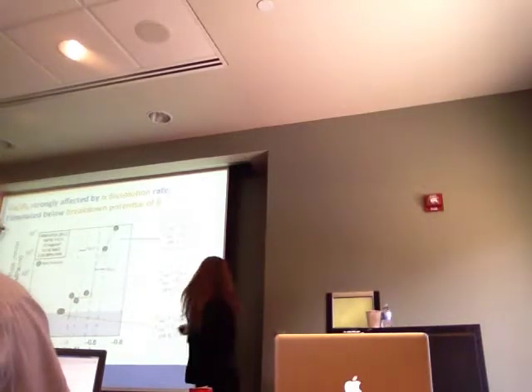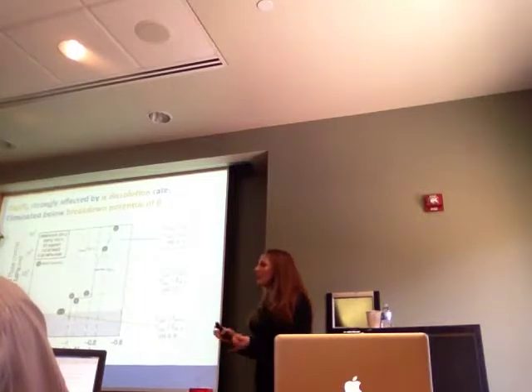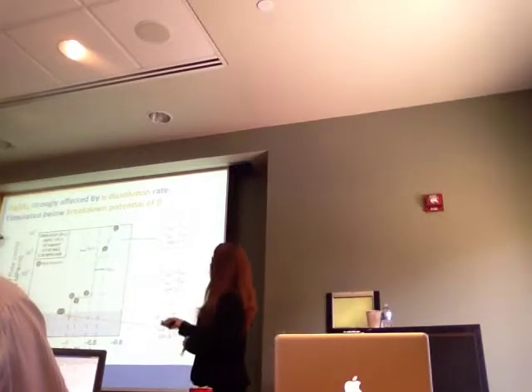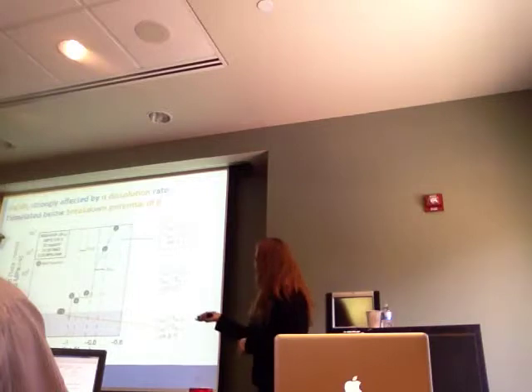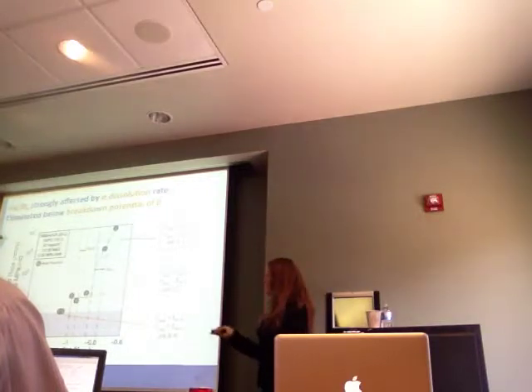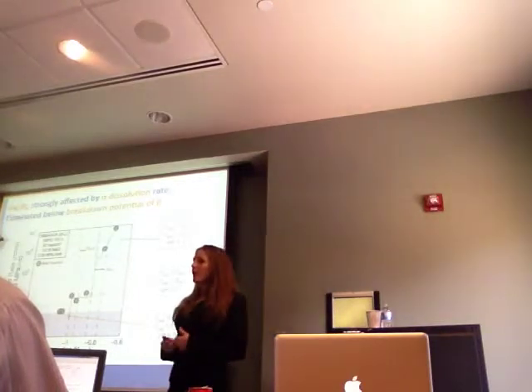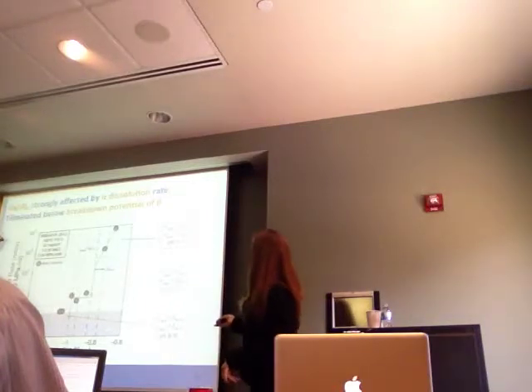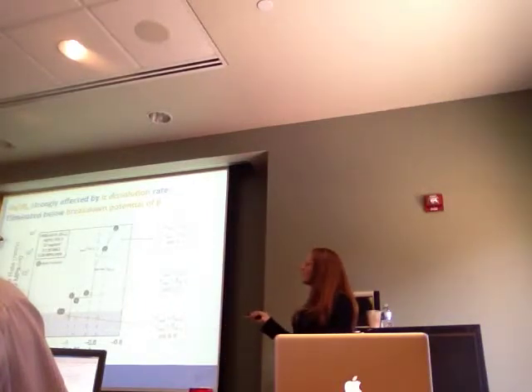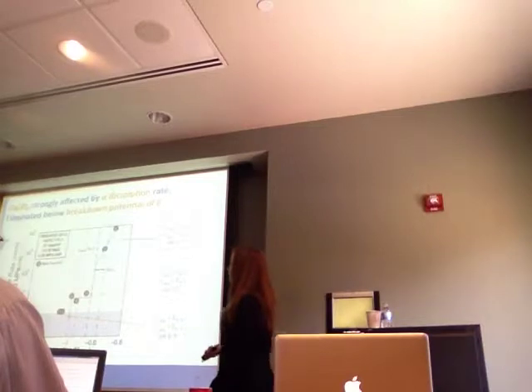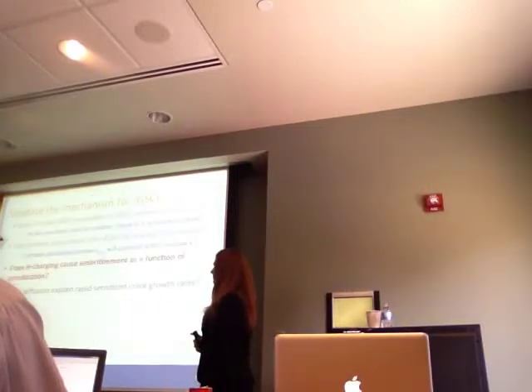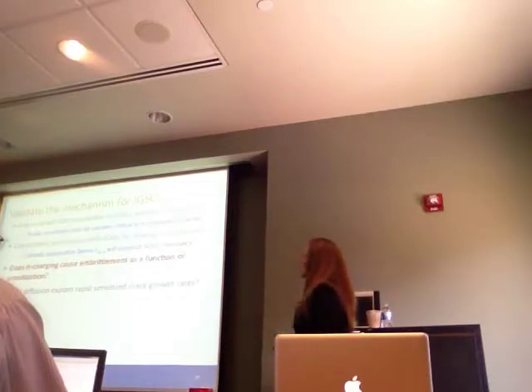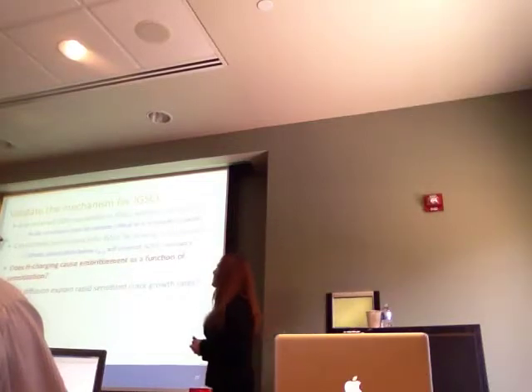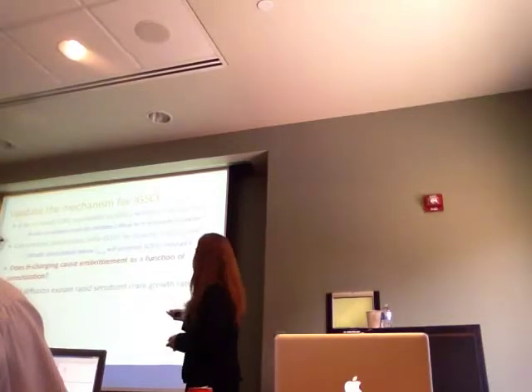So to drive this home, when you're above both breakdown potentials, your crack growth rates are very fast. When you're between these breakdown potentials, you only have beta dissolution. Your crack growth rate is slow, but it is measurable. Then when you're below both breakdown potentials, your crack growth rates are pretty much in the resolution limit. And you can see that these also correlate with your pH. All right, so that's our second validation point. Yes, cathodic polarization can promote intergranular stress corrosion cracking resistance.